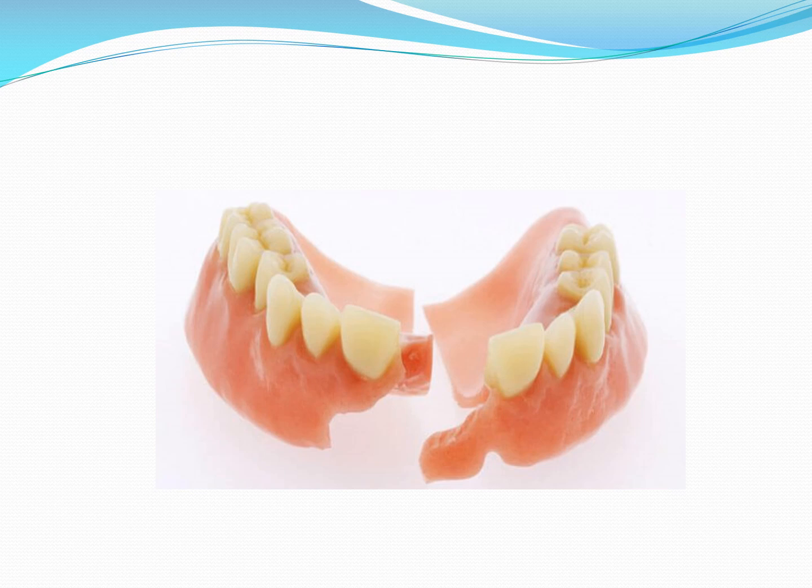Wax should not be placed over the fracture site, for better visualization of the accuracy of the assembly. The accuracy of the assembly is carefully verified by visual inspection. After we have assembled the fractured parts, then we pour the cast. Undercuts in the denture are carefully blocked out. Plaster is poured into the denture to make a cast.